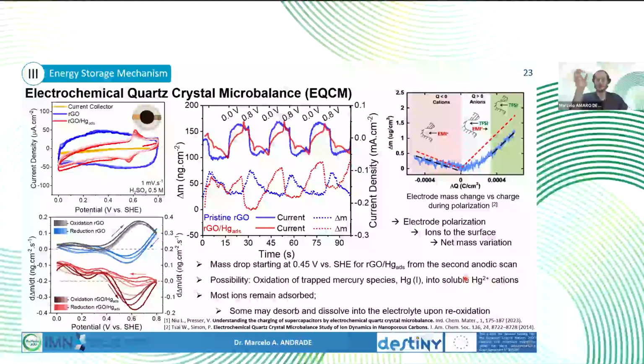And then since we are polarizing it positively, that could locally repel the mercury 2+ cations that then are reabsorbed, right? And that is what possibly causes this reversible mass variation. So it might desorb and also dissolve into the electrolyte irreversibly, and that's why we see a decrease in capacity also from the beginning.